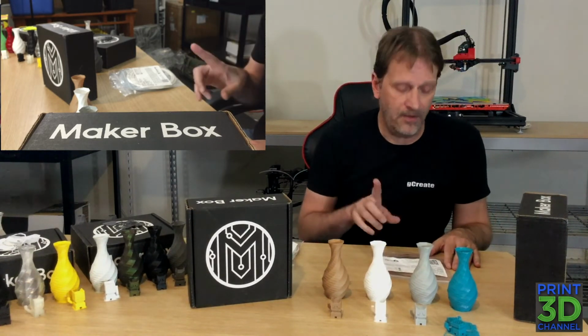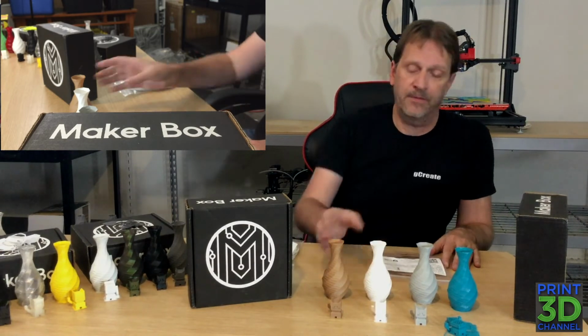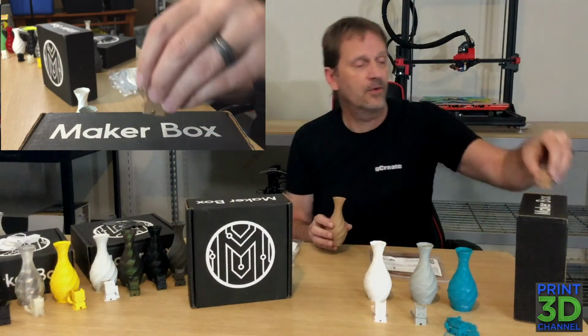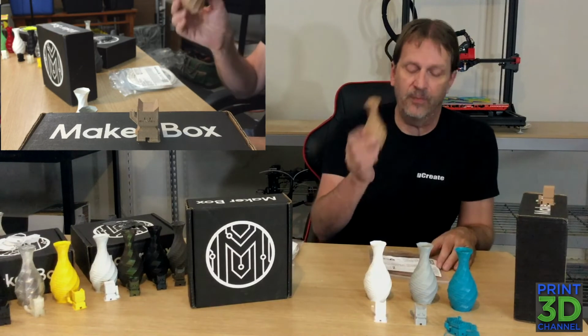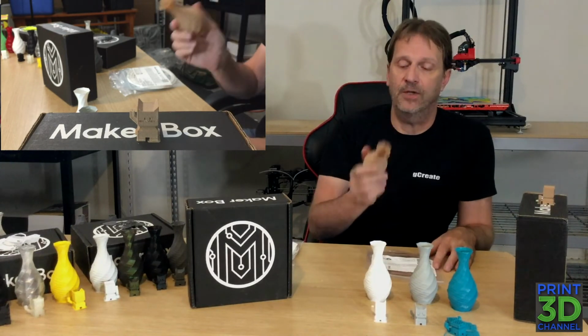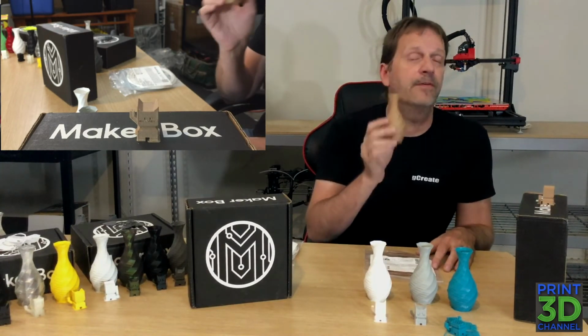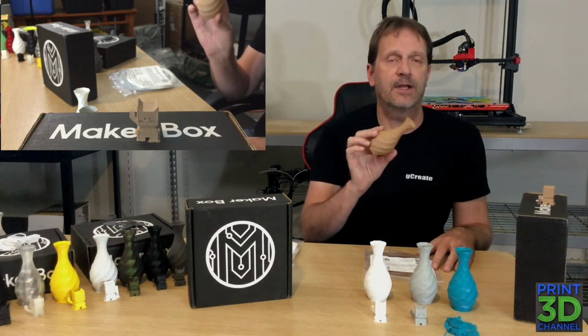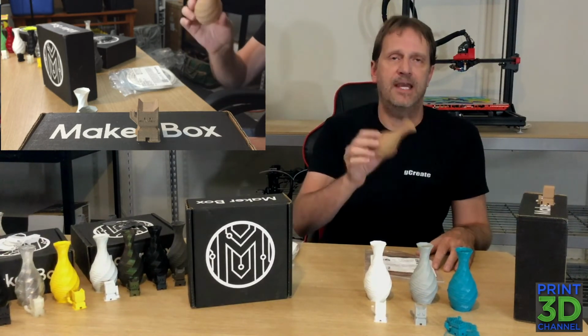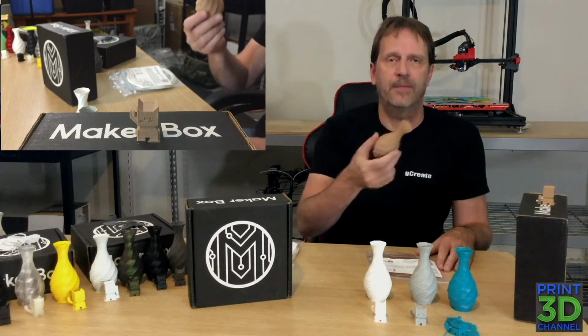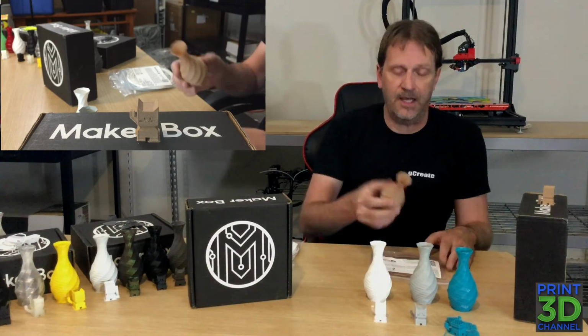And it's best to print this with large layer heights over 0.2 millimeters, and of course a large nozzle, and of course a hardened nozzle, because this particular type of filament, Push Plastics' wood fill, actually has wood pulp in it. And it can be sanded and stained, which is great because that's the kind of wood fill filament I like to find for projects, where I want to stain them after and give them a really wood type finish in the end.